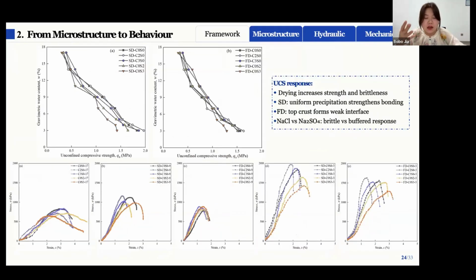And in terms of the unconfined compressive strength, before drying, the samples show relatively high plasticity due to the combined effect of matric and osmotic suction. After drying, both strength and brittleness increase significantly. If we look at the influence of drying modes, differences appear.